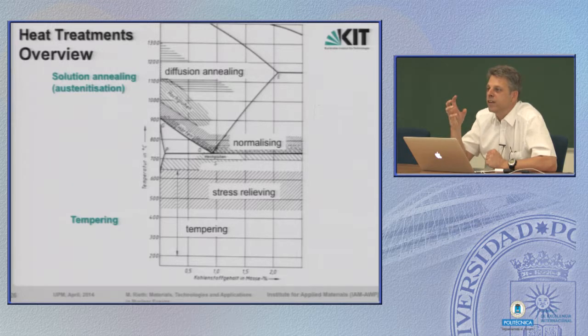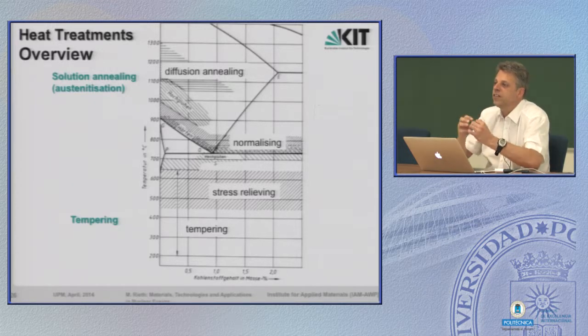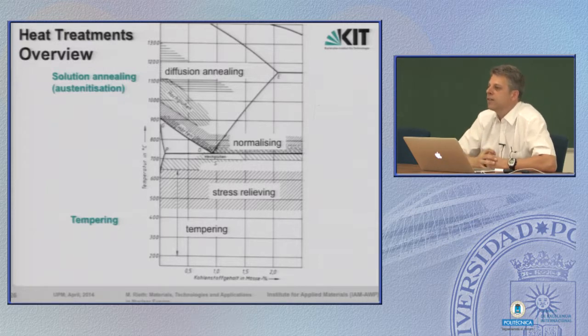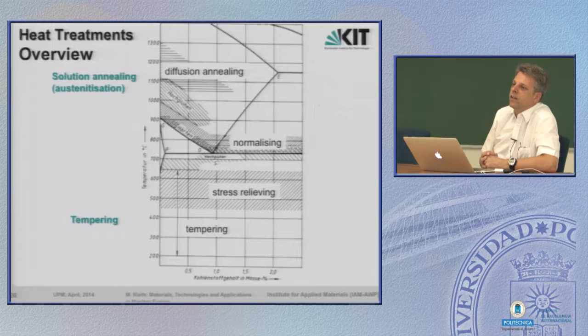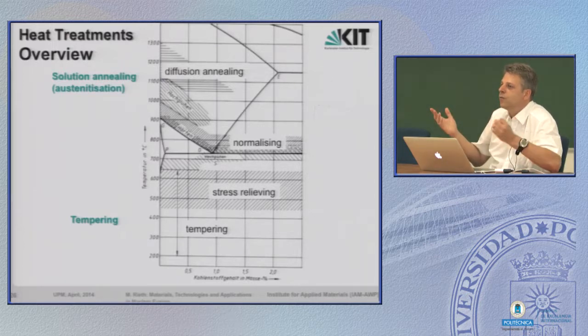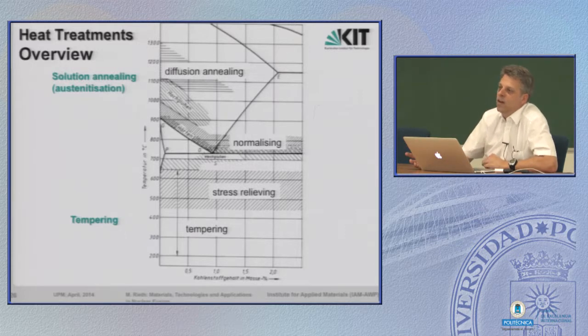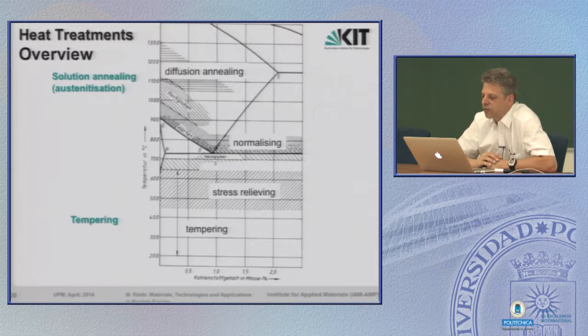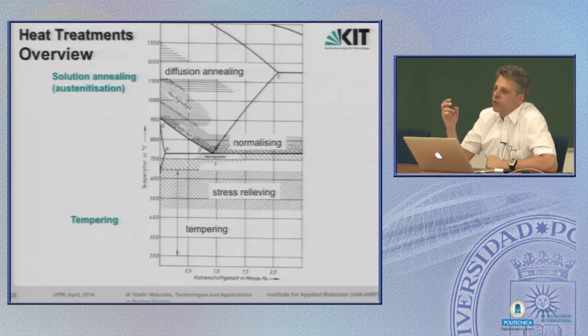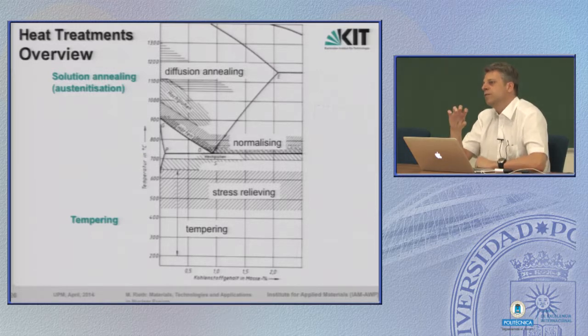So there is no reason for the lattice to be bent, so it is relaxed. It goes nearer or almost into an original BCC-structured lattice, and then the reason for this very hard and brittle martensite phase has gone, and what you have left over is still the martensitic microstructure with all these laths or lancets or whatever you call these fine structured things you have in the martensitic microstructure. But since the carbon has gone out, it's softer than it was. It's not as hard anymore, it's softer and more ductile.